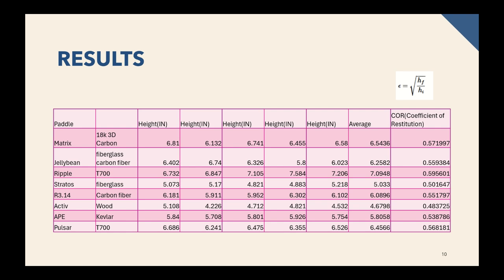Overall, the T700 material paddles did the best, with the highest score coming from the Ripple paddle that was made of T700, and the second place was actually from an 18K 3D carbon fiber paddle that was not T700. And in last place, of course, based on its Young's modulus, was the wood paddle, which had a maximum height of less than 5 inches and a CoR of less than 0.5.